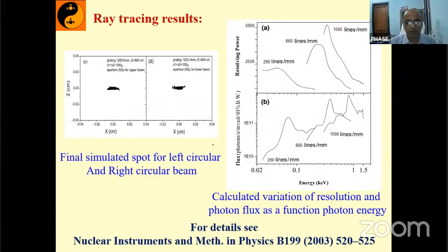So that way you can get left circular polarized light and right circular polarized light. The main condition is that the beam intensity should be the same under both beam directions, for the left circular and the right circular. This is confirmed by our theoretical calculation that whenever we move the aperture, we get the same kind of beam. It is basically the mirror image of the first beam. So the left circular beam is this, and the right circular beam is this way. So this is exactly identical.